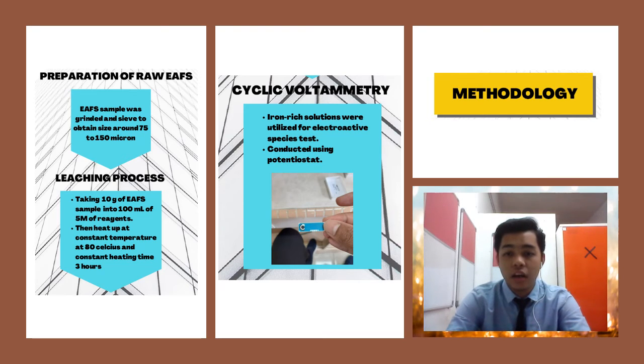After that, the iron-rich solution from the leaching process was utilized for the electroactive species test. This cyclic voltammetry study was conducted using a potentiostat and a screen-printed carbon electrode, like the figure that has been shown.